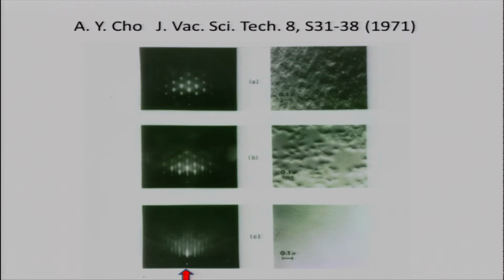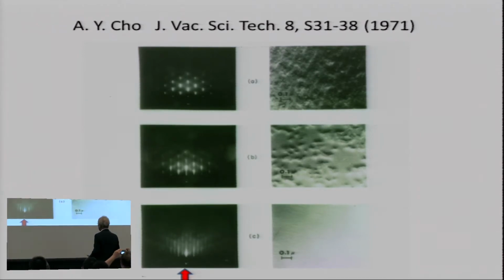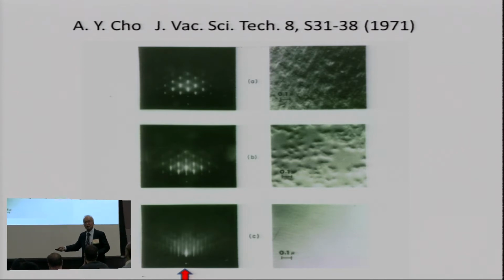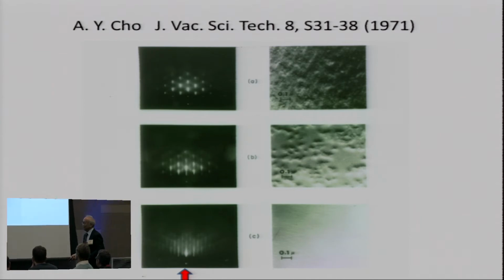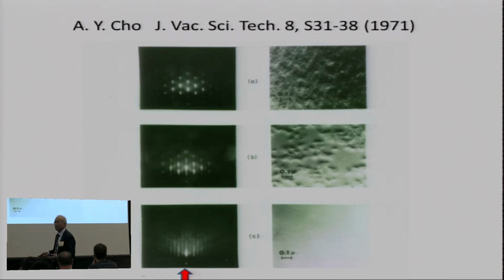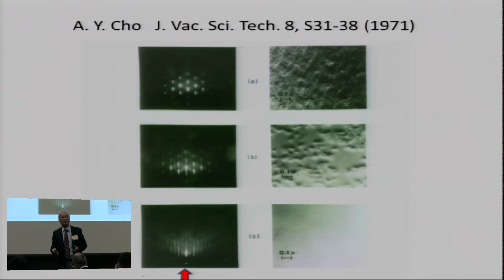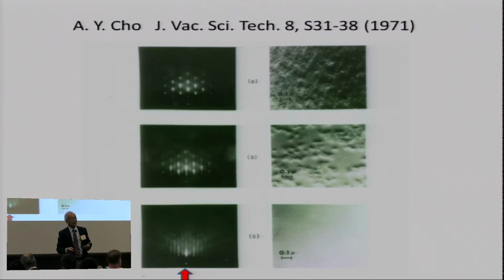Now, in the same year, 1971, I also reported the diffraction pattern on the left-hand side, and then the corresponding surface structure. Look at the carbon replica on the right-hand side. When you have a gallium arsenide surface, you clean it with bromine methanol, and you think it's very clean. You put it in the MBE system, heat it up, dissolve the oxide. What happened? You look at diffraction patterns: spotty diffractions. The reason is that after heating up, they have microfaceting.